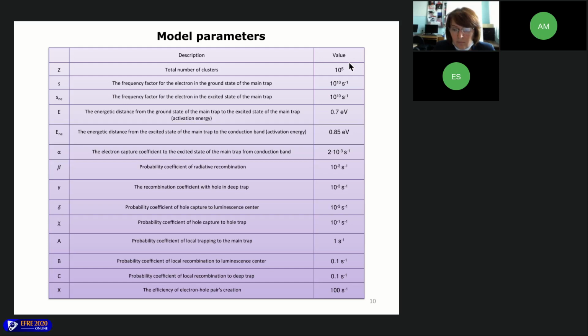I can estimate that such a number can be contained in maybe a cubic micrometer or less, so you can estimate the concentration of such clusters and concentrations of such defects. It is around 10 to the power of 12 or 15 defects per cubic centimeter. And so the cluster size is around a micrometer or less.